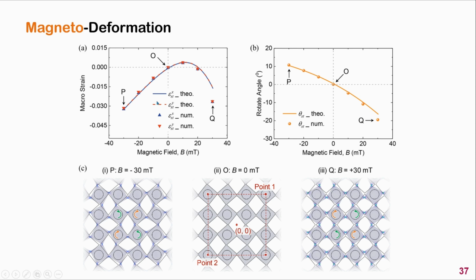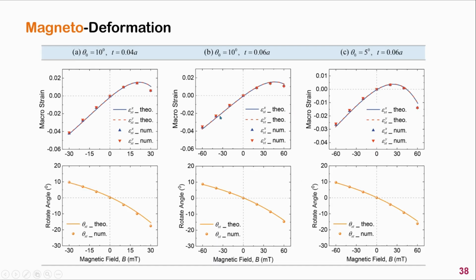The left plot is for the macro strain. In finite element simulation, the strain is measured by comparing the displacement between two target points, as is shown here. And the right plot is for the rotating angle of the square unit. We can see that our theoretical method works very well. We also did the comparison for other geometric parameters. In each case, the analytical predictions agree very well with the finite element simulations.